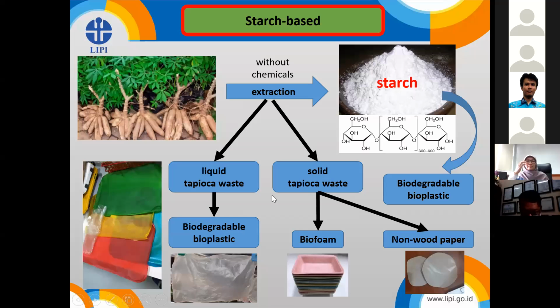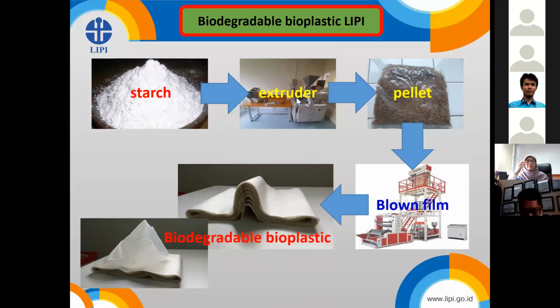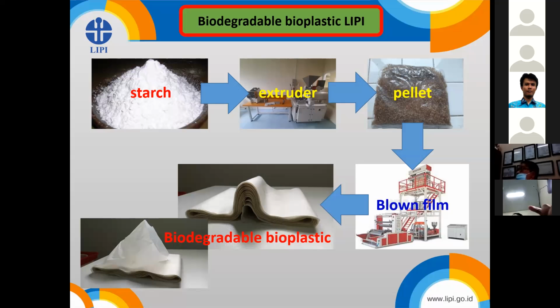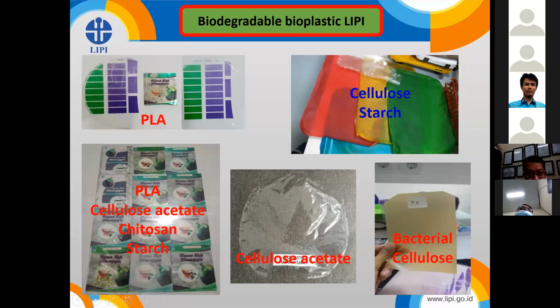The first of our products is biodegradable plastics. This is the extruder in our lab. In the extruder, we mix starch with several additives such as plasticizer and compatibilizer or others to produce biodegradable bioplastic pellet. And the resulting pellets are then blown using a blow machine to produce biodegradable bioplastic bags for further application. In addition, we also develop several products from PLA, cellulose acetate, chitosan, starch, and also, like I said before, bacterial cellulose.